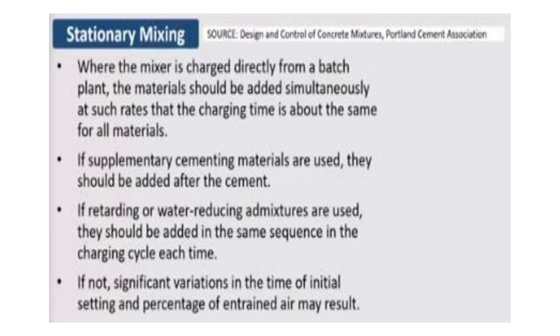So first, basically, we have to add the aggregates. Then we have to add cement. Before that, 10% of the water has to be added, and during mixing, the water has to be added in a planned sequence. And after the cement, we have to go for water reducing admixture and supplementary cementitious materials, but in a proper sequence, which should not be altered.